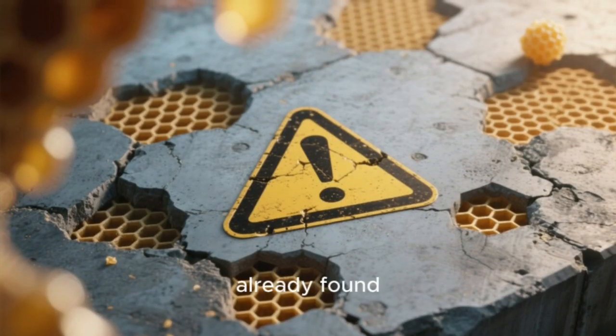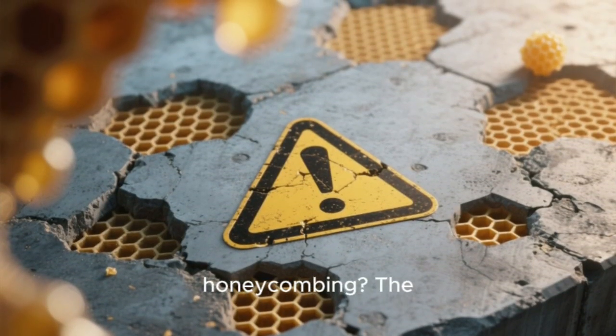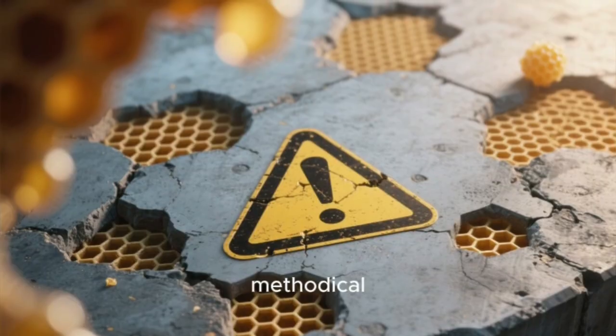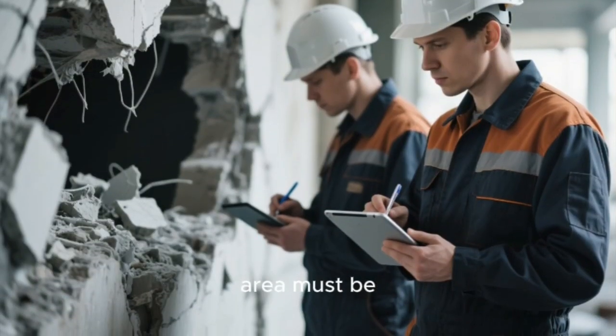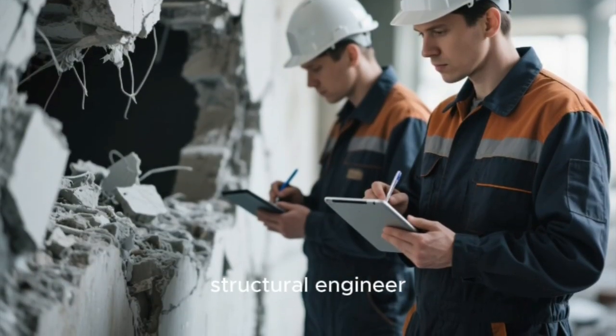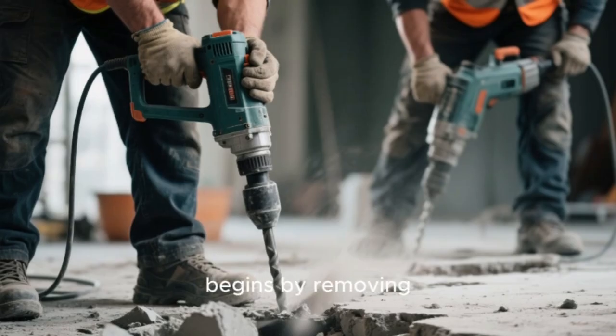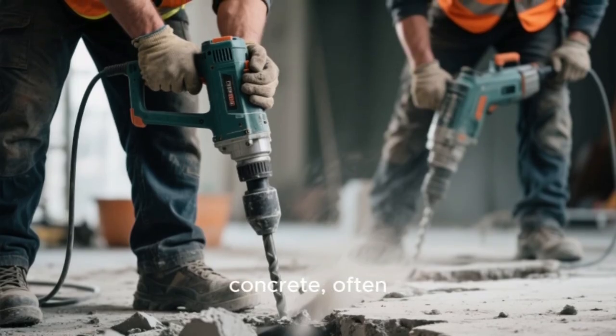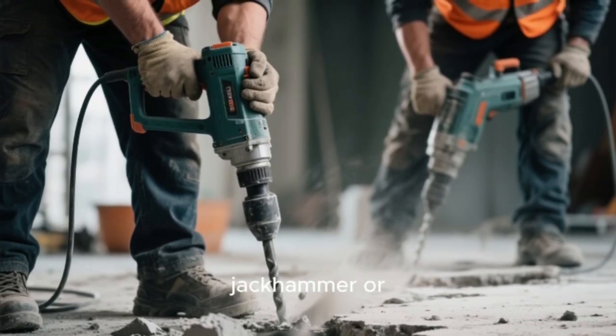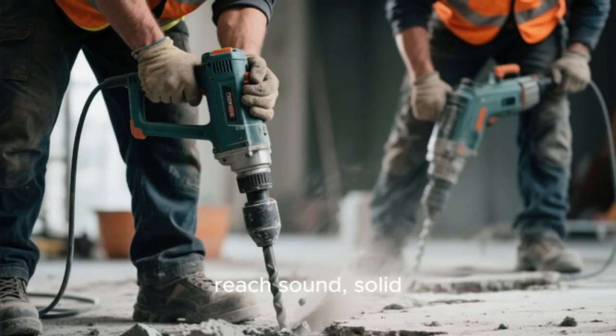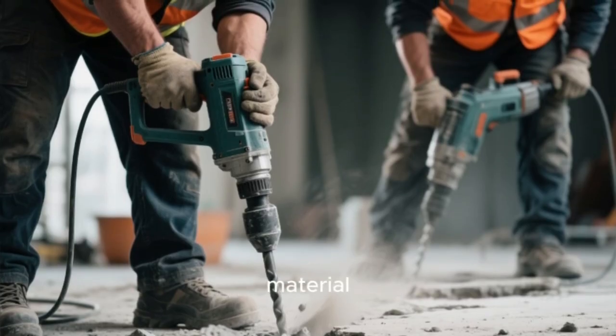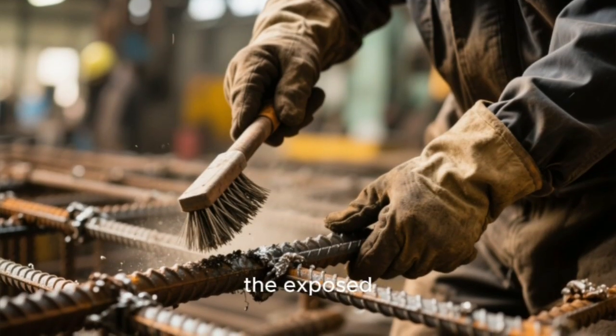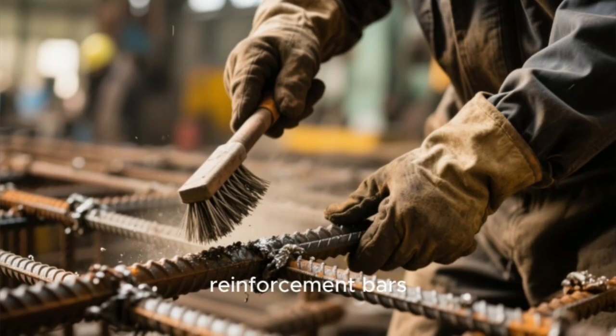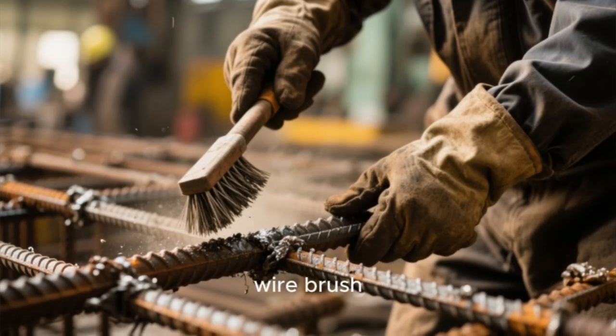But what if you've already found honeycombing? The repair process is methodical. First, the affected area must be assessed by a structural engineer. Then, the repair begins by removing all loose and weak concrete, often using a small jackhammer or scabler, until you reach sound, solid material. The next critical step is to clean the exposed reinforcement bars of all rust using a wire brush.